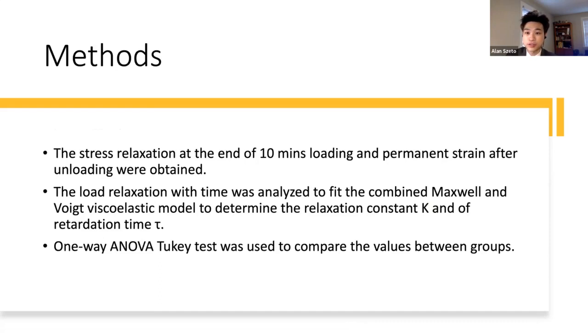The stress relaxation at the end of 10 minutes loading and permanent strain after unloading were obtained, and the load relaxation with time was analyzed to fit the combined Maxwell and Voigt viscoelastic model to determine the relaxation constant, capital K, and the retardation time, tau. And then one-way ANOVA with Tukey test was used to compare the values between different groups.